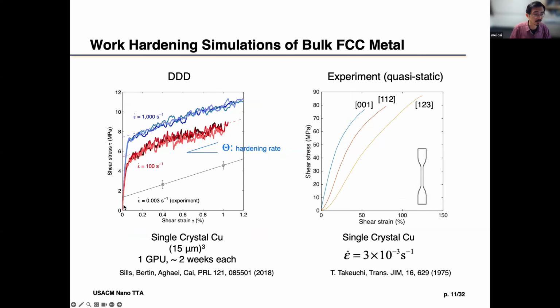You can see that initially it's elastic, but then it yields. But after it yields, you can see that the stress keeps increasing. The flow stress keeps increasing in order to keep the plastic deformation going. That is called the strain hardening phenomenon. And the slope of this curve is called the strain hardening rate. You can see that we can run the simulation repeatedly and get a pretty robust prediction of the hardening rate. That was quite exciting, because before that, we were spending months of computation and we were still down here. So now we get a pretty robust prediction of strain hardening rate.